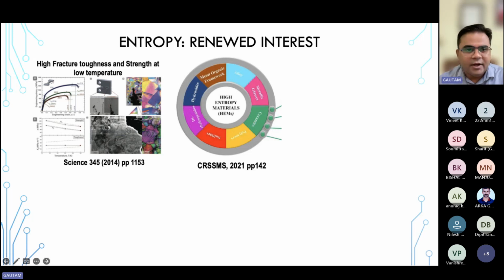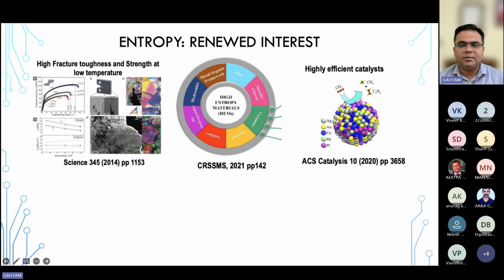So this is not only the structural property. I mean, any kind of material's success is decided by whether that particular material can be applied to challenging situations where other materials may struggle, or new applications can be discussed for that material. So this is a structural application. Now, another interesting thing is that people are talking about using this concept for developing highly efficient catalysts. So we know palladium is an interesting catalyst, but it is expensive. So they used this concept of generating single phase nanoparticles using different elements such as silver, gold, copper, and platinum, and they were able to form single phase nanoparticles there. Interesting part is that, of course, silver is also not very cheap if you compare with any structural material, but we are talking about catalysts here. So it's certainly cheaper than palladium.